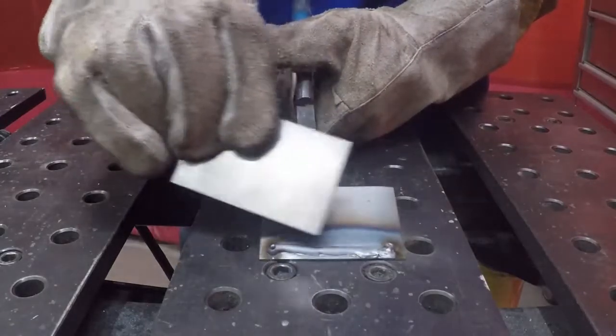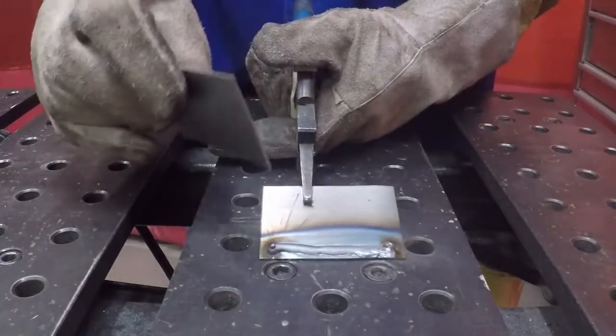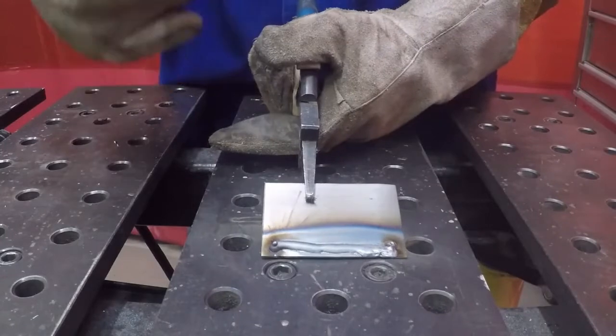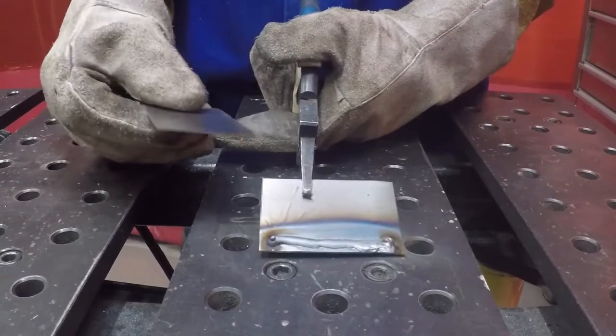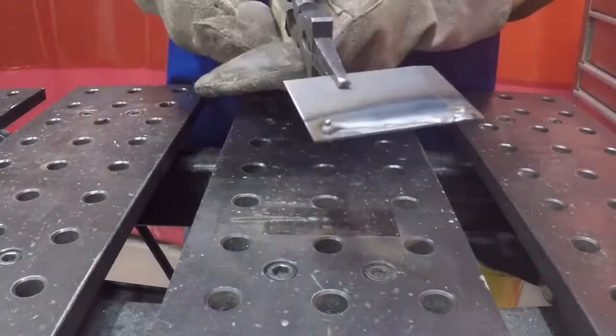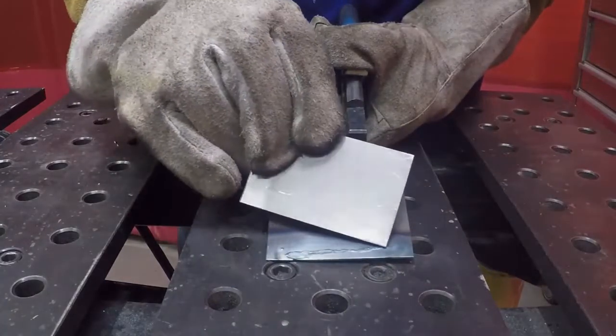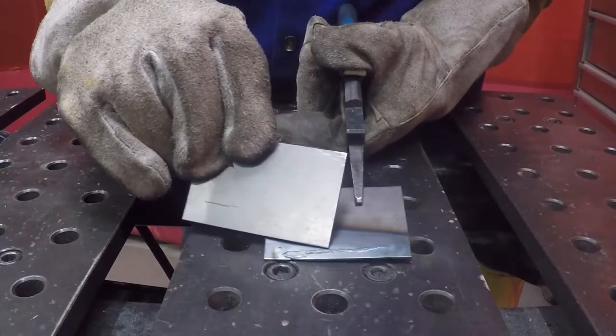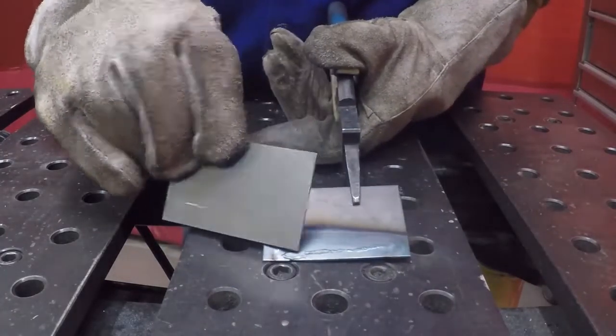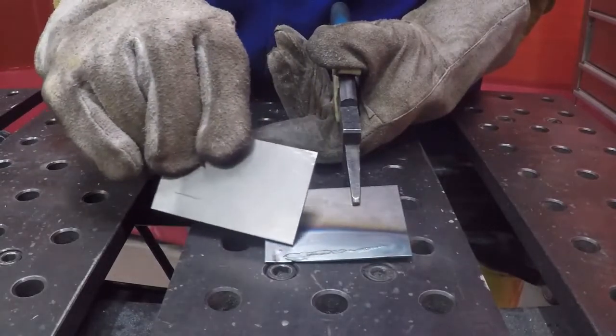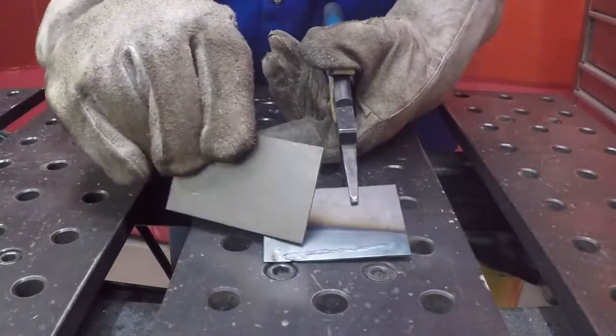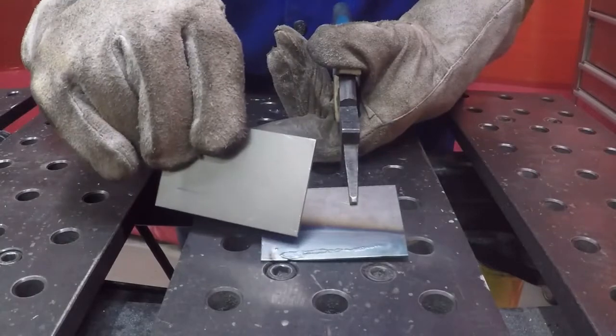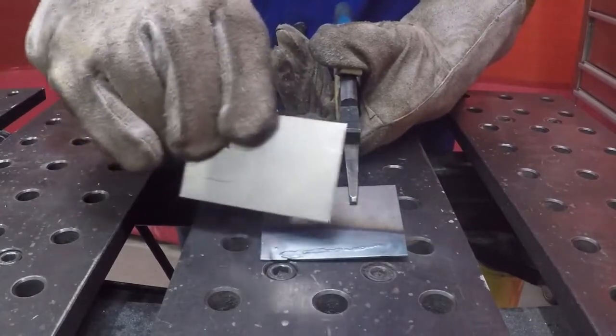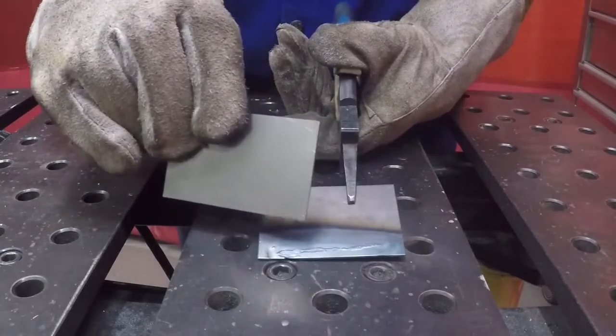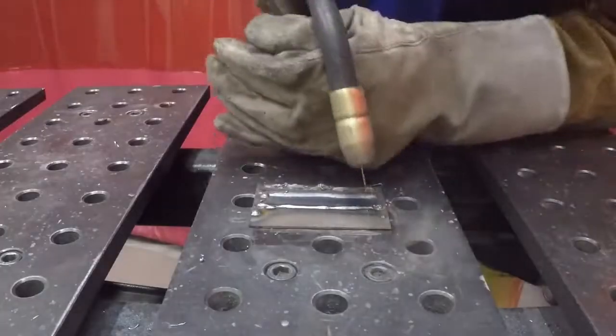There are no inclusions in it, no air bubbles. I didn't have any pops or sputters. The weld did have that frying bacon sound, which is what you're looking for when you're making a MIG weld. And you can tell that I started here and actually went a little slower as I got across, so my penetration went up. We want to avoid penetration like this here at the end. That much penetration can contaminate the backside of the weld, and if this was a structural piece, that could give us a poor weld to start with here.